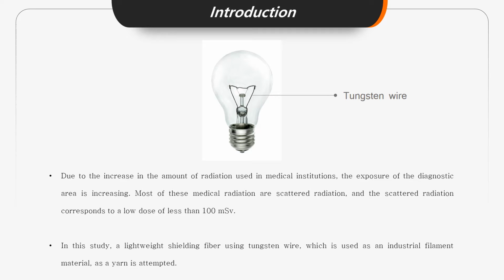In this study, the lining of radiation shielding clothing that can protect from indirect dose was developed. Most of the shielding clothing linings are in the form of sheets and they can easily get tired due to their heavy weight. In this study, it was intended to be made in lightweight fiber form using tungsten and eco-friendly shielding material. Tungsten is an eco-friendly shielding material with a high density of about 20 and has been usefully used as a substitute for lead in various recent studies. Tungsten wire on industrial filament was used as the main material, and a shielding fiber was manufactured using this as a yarn.